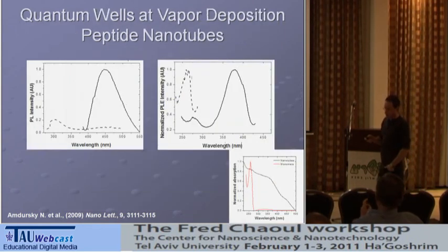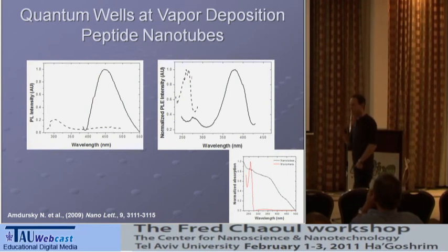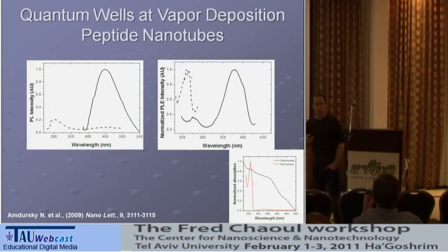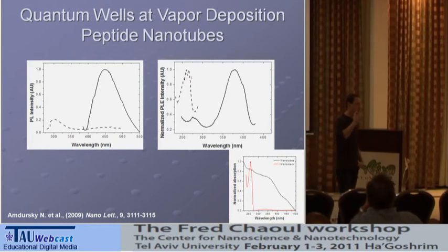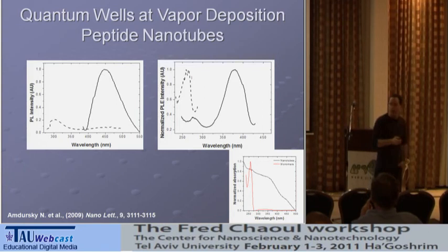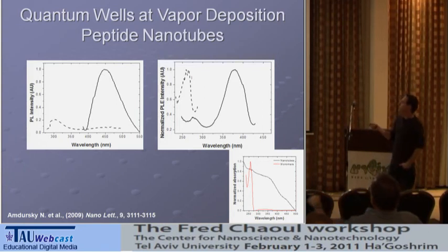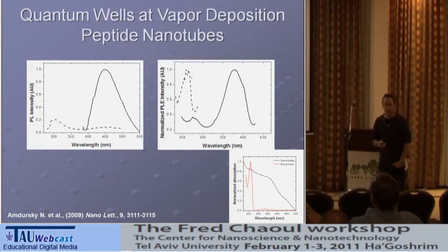So it also has a different optical absorption spectrum, and it also has different photoluminescence properties. The photoluminescence of the exciton of the quantum dot is in the UV. But suddenly, here we can also see a strong photoluminescence in the blue region.